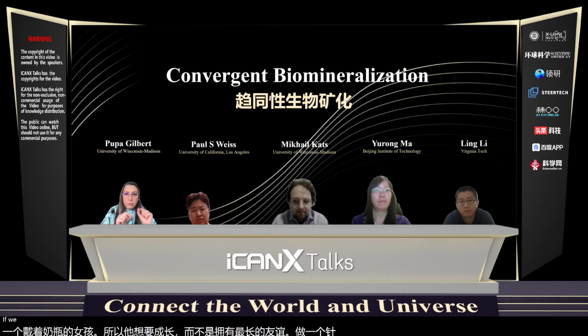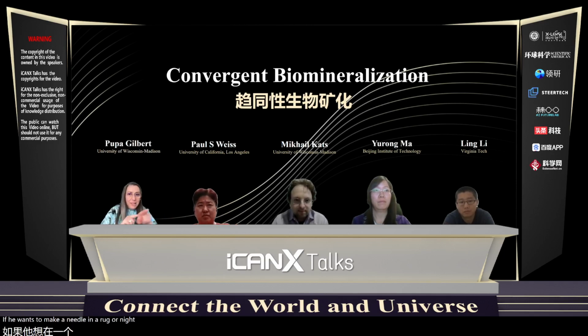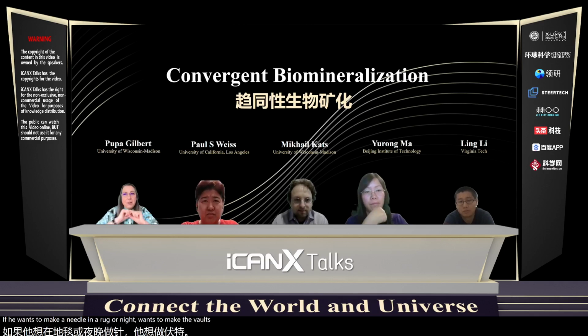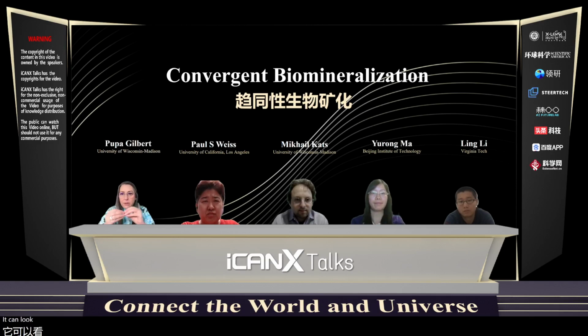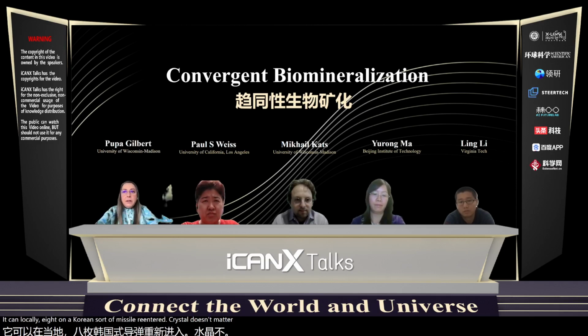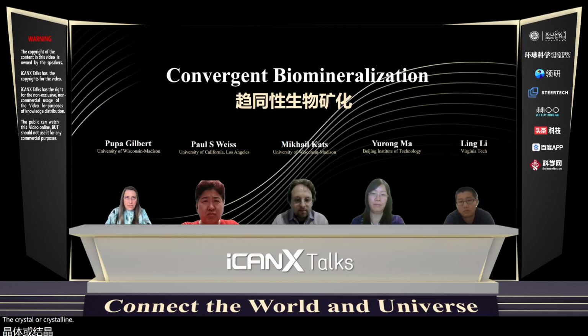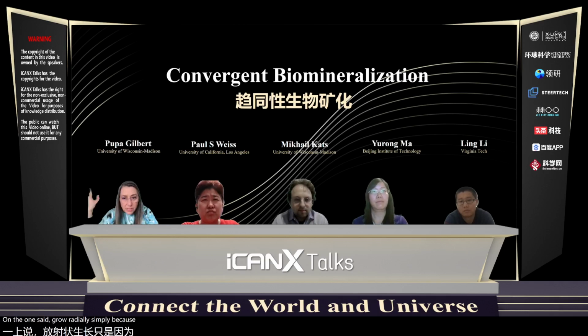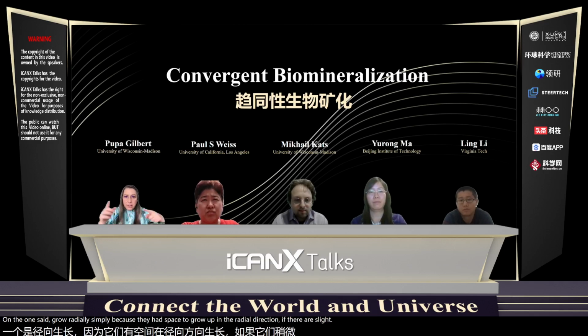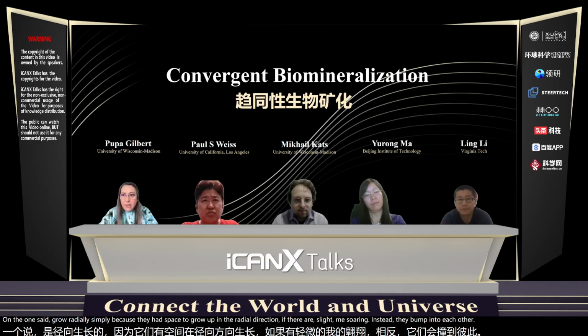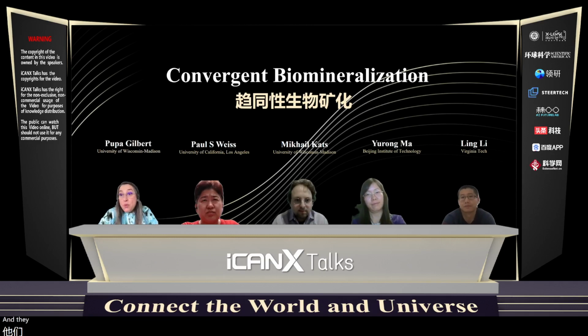If it wants to make a needle, and aragonite wants to make needles, then it will grow spherulitically. It can nucleate on a co-oriented or misoriented crystal, doesn't matter. The crystal orientations that win are the ones that grow radially, simply because they have space to grow in the radial direction. If they're slightly misoriented, they bump into each other and they don't grow big.